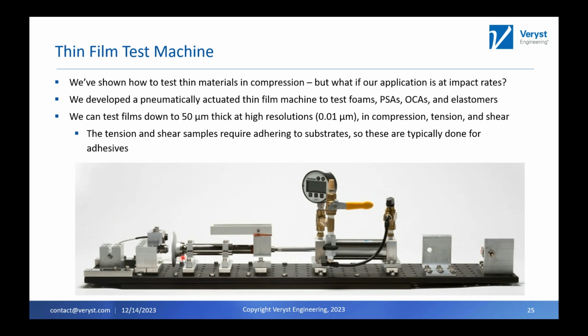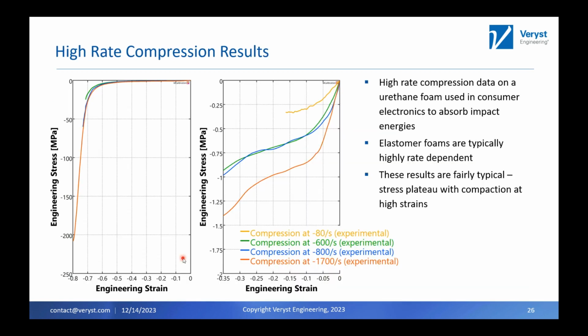I don't want to go into that today because we're really going to be talking about compression on these thin materials. So I'm going to show some data on a foam material that we tested, and I believe this foam material was a little on the thicker side. I think it was 400 or 500 microns thick. So on some of the other things we're talking about here, this is pretty thick compared to the 3-micron film I mentioned earlier. But this is the stress strain result for these on this machine, from a strain rate of 80 per second in compression to 1700 per second in compression.